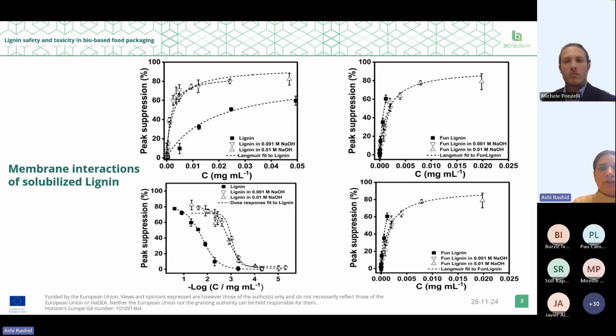Percentage peak suppression is then plotted against the concentration in the form of calibration curves, and this concentration is taken from the HPLC analysis. Calibration curves are presented here for both the lignin and the functionalized lignin. To increase the solubility of lignin, different concentrations of sodium hydroxide were also used in an additional set of experiments, and peak suppressions were calculated, and calibration curves were derived.